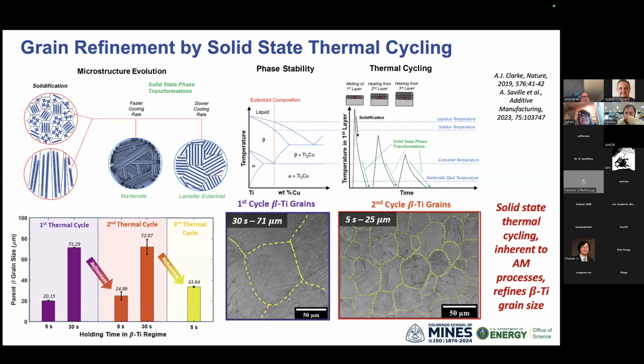So one of the things we postulated is that, in addition to solidification, you might also get grain refinement in the solid state by thermal cycling during additive manufacturing. So one could imagine whether or not you produce equiaxed or columnar grains during solidification, if you then go through the solid state transformation, as shown here, with a fast cooling rate, you make martensite. With a slow cooling rate, you make eutectoid, much again like pearlite in steels.